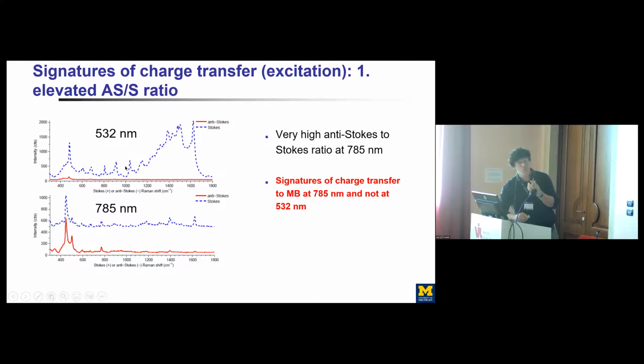On the other hand, now if you shine the same intensity at 785 nanometer, that's essentially less energy, same intensity, but you're putting less energy in the system, you actually see that your anti-Stokes is quite strong compared to the Stokes. So what this would suggest is that we have a very high anti-Stokes to Stokes ratio at 785, and this would indicate that at 785, we might actually have a charge transfer taking place, or that excitation at the interface taking place, and at 532, that's not happening.